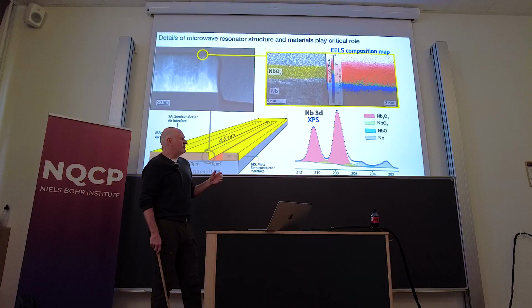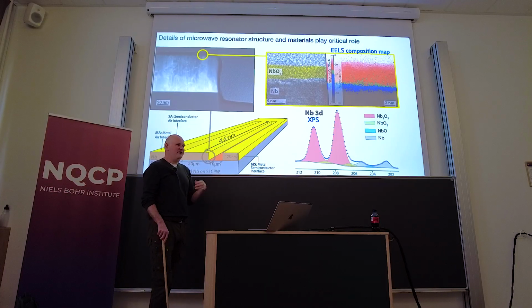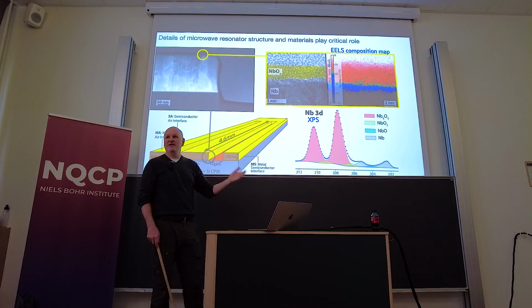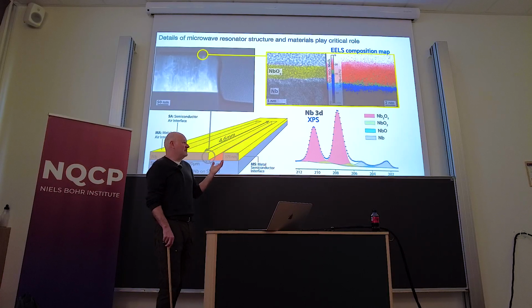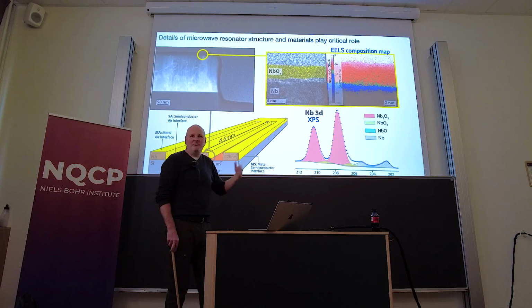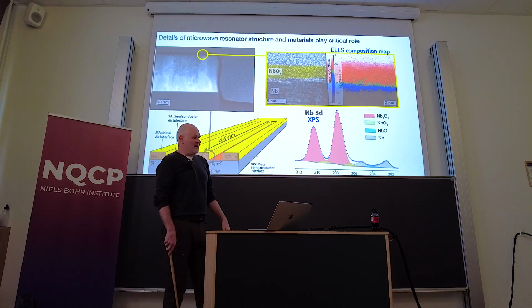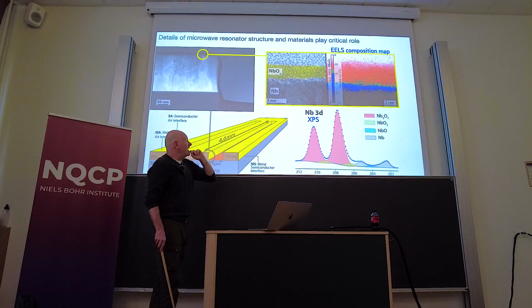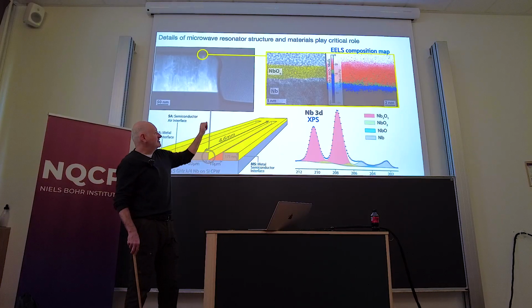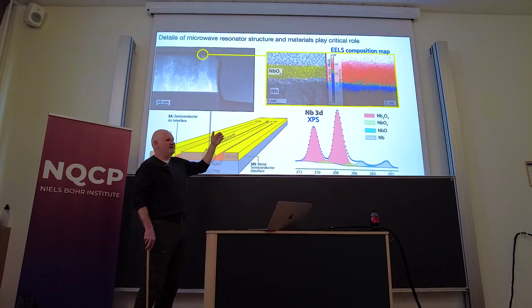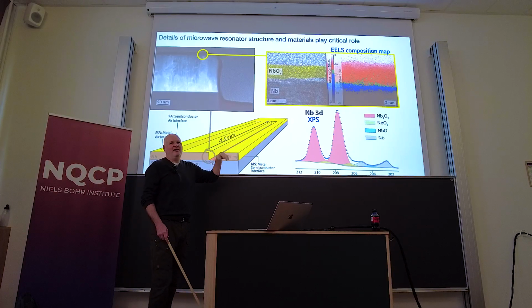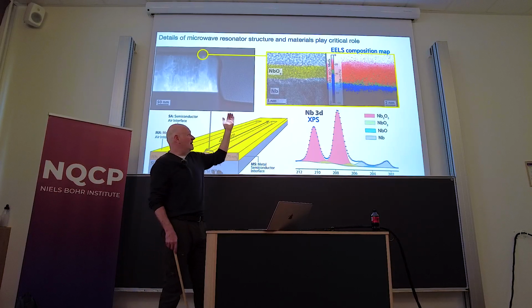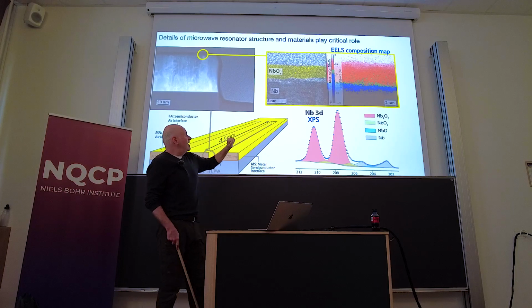And the general practice at the time was that you just sort of left it there and assumed that it didn't really do anything, because in theory, it maybe shouldn't. Niobium oxide isn't a super lossy oxide by itself, so everyone assumed, fine, good enough. But what we did is we actually, in cross-section, made this EELS composition map. So for those of you who don't know, EELS is essentially a TEM technique that allows you to make an elemental map.